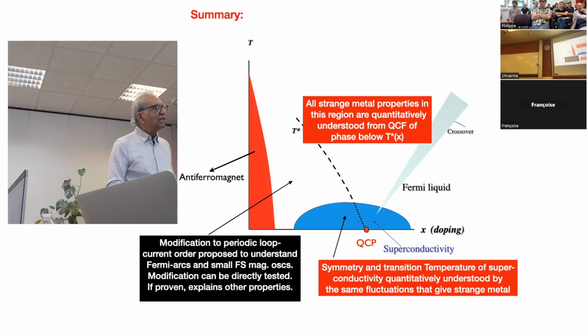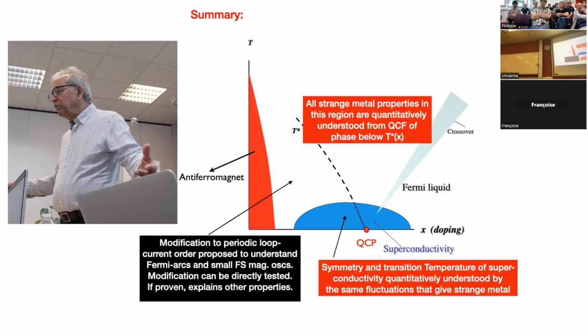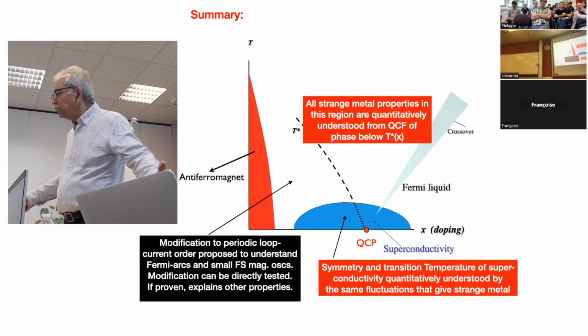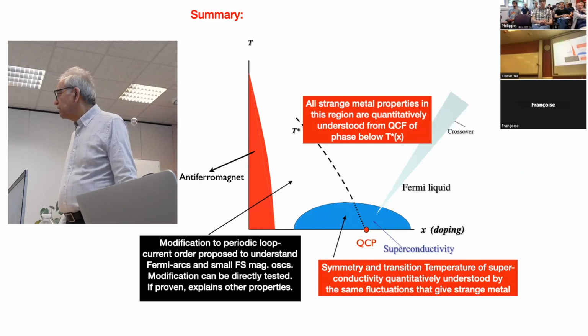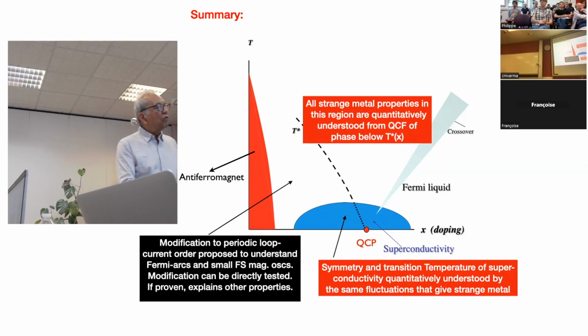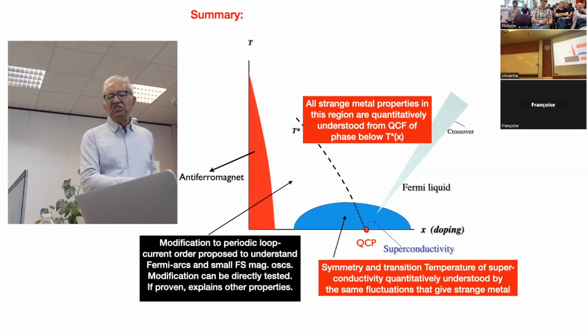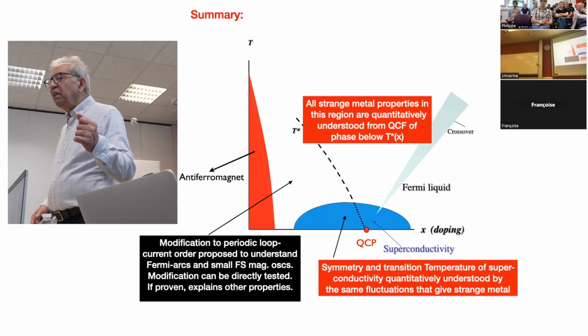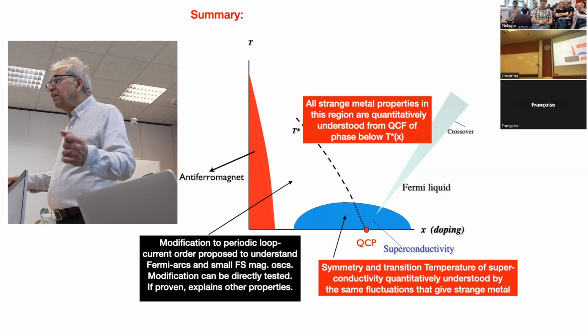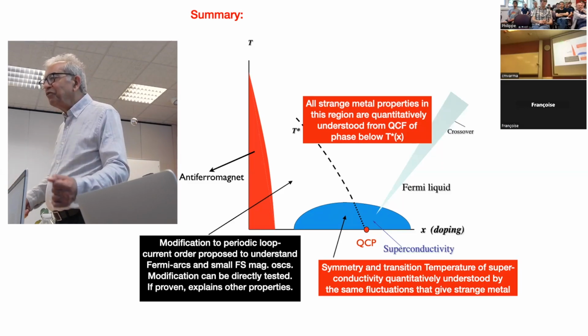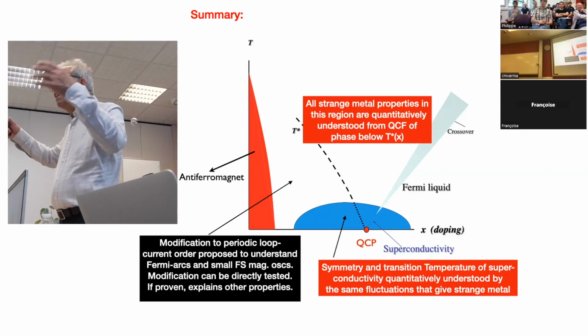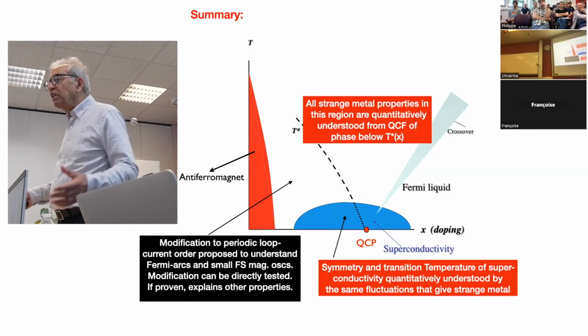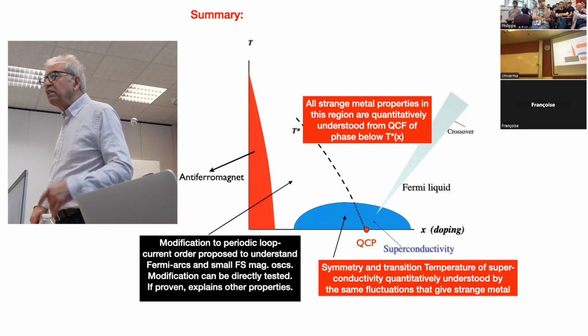If this thing exists, I've drawn this thing very roughly, precisely what the crossover is. It should be a Fermi liquid, and indeed it's consistent with a Fermi liquid. One can prove, with a little statistical mechanics, that if there is disorder and the critical point has a dynamical exponent infinity, the effect of disorder is to smear the critical point over a region, okay? And in some other contexts, in heavy fermions, that is observed. And here I need a modification of loop-current order with a period of a certain size, but what they are seeing is a period, and there is a magnetic field, it appears, but the period is at least a factor of two longer than what I would like. So that's the status of understanding of this field.